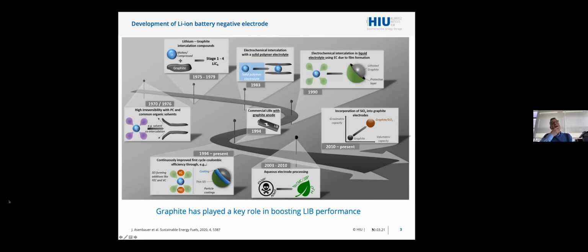The anode, definitely, graphite definitely played an extremely important role in the development of lithium-ion. I mean, it was not always used. At the beginning, there were several problems with graphite for lithium insertion because pure graphite tended to co-intercalate also the solvent molecules, and this resulted in the destruction of the graphite structure. So actually the first commercial lithium-ion cells used hard and especially soft carbons. But finally in the 1990s, it was identified that EC could prevent the exfoliation of graphite, and then in 1994, the lithium-ion batteries using graphite electrodes were commercialized.